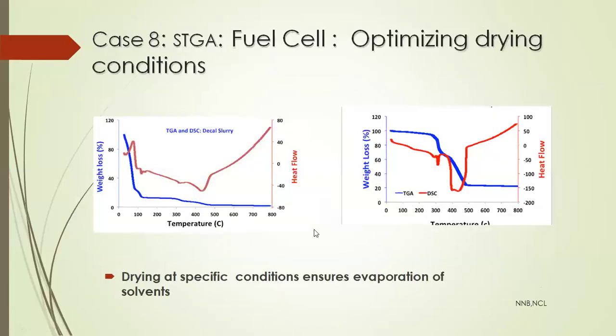supplier here also. We have used TGA beautifully in defining the drying conditions of our electrode. This is the electrode which was failing in the fuel cell atmosphere. And when we did a TGA of that, we found that there is a huge weight loss below 150 degrees centigrade.